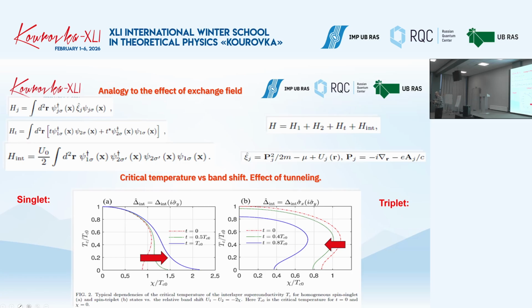Why? It's quite clear. For triplet pairing, the key point which allows these pairs to exist is that they are separated in different layers. This helps us to avoid the destroying effect of the Pauli exclusion principle. When we switch on tunneling, we kill the pairs. This is why, increasing tunneling, we suppress this triplet channel.